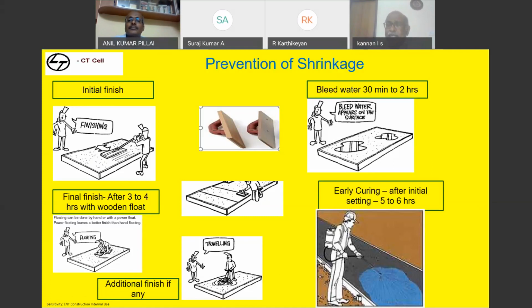By this, you are allowing the concrete to crack, whatever cracks happen in this state. By doing a secondary finish, tapping, you are closing the crack, because the crack, whatever it has formed, is hardly 0.5 millimeter in width and maybe 2 to 3 millimeter in depth. So when you tap the surface, the slurry that accumulates will close the crack, and the concrete will not crack further because you are allowing it and you are closing the entire phenomenon.